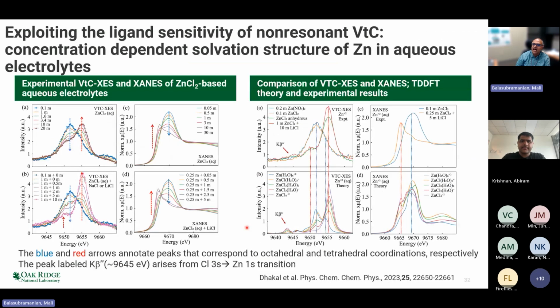So within emission, the last emission study that I would want to just quickly mention is this ligand sensitivity of valence to core. The valence to core X-ray emission is very sensitive to the surrounding ligand. And as you can see, the chlorine in this case of the zinc chloride, which is measured for various concentrations, appears at a different place when compared to the zinc oxygen from the solvent. So one can use this to speciate and differentiate between ligands of different types. And this can actually be done non-resonantly, and non-resonantly you can even perform it with lab sources. So that is a big field that is now developing, and there are many places where people are utilizing lab-based non-resonant X-ray emission as a very prominent tool in their research.